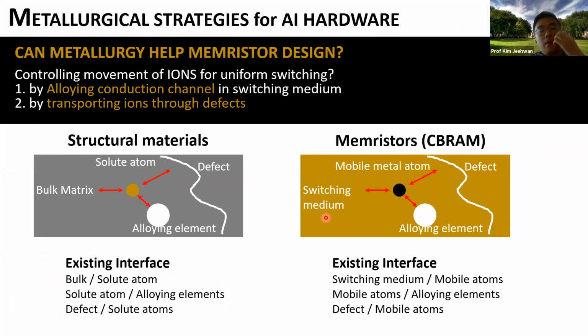Okay, first have a look at this. Like structural material guys have done, we try to mimic this strategy to have a control in memristor. First strategy we have used is the alloying conduction channels. Like I just mentioned, inside the switching medium, we form the conduction channel. And I just mentioned that conduction channel is very, very unstable. So we try to put some alloying element to stabilize these mobile metal atoms inside the memristor. Okay, that is the first strategy, borrowed from the metallurgical solution.